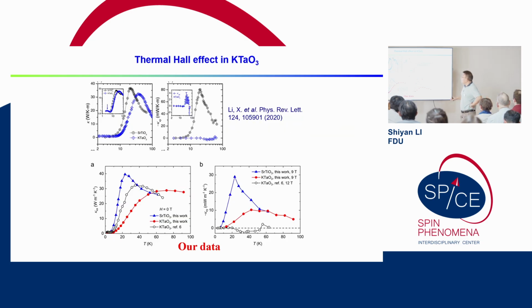And there was another negative result for KTO in Professor Behnia's group when they did the measurement of STO. They found that the thermal Hall signal is very small, almost zero here and a little here. So we bought the single crystal and did the measurement again. We found that there is also a thermal Hall signal, maybe only half of the STO.